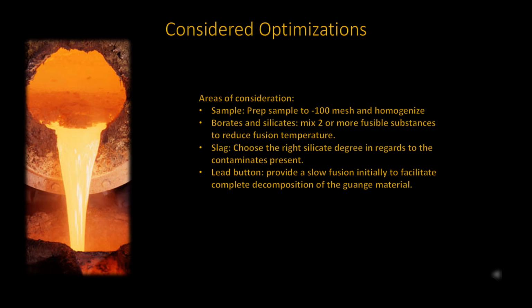This allows for the formation of the lead globules and gives enough time to collect all the precious metals. Near the end of the fusion process, the temperature is increased to superheat the material at about 200 degrees centigrade above the formation temperature of the slag. More in regards to the silicate degree in an upcoming presentation. However, a monosilicate slag is used as reference.